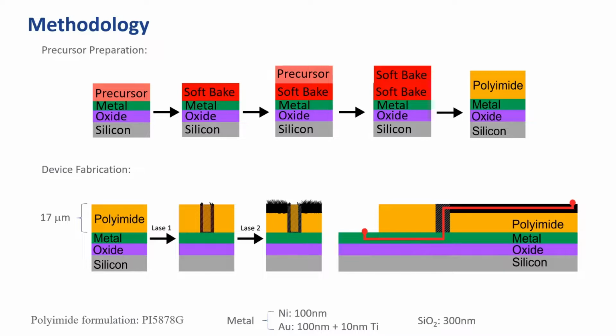The laser process is then a two-step self-aligned process where the first is at high laser power and low scan speed used to ablate the polyimide in the film, and the second right then converts the top surface polyimide into high quality LIG while converting the sidewalls and remaining base material towards high quality laser induced graphene. The result is a continuous pathway from the top surface LIG to the underlying metal, mediated through the contacting structure, which we call a contact plug.